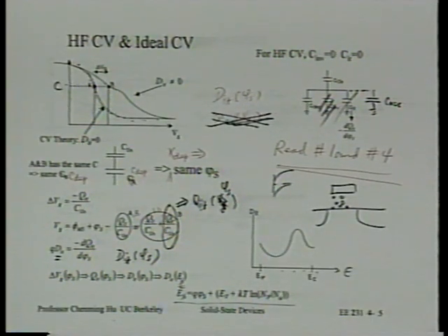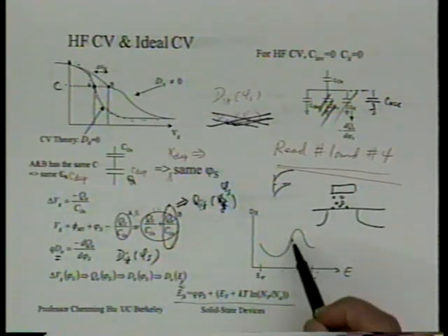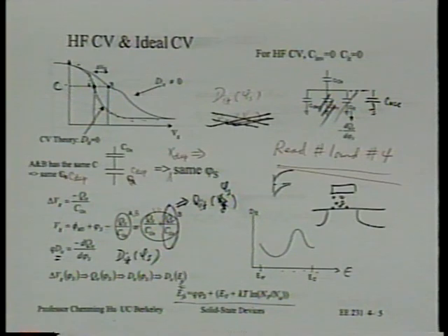When you see this peak, in my mind, I consider it really a discrete energy level, but because of our measurement inaccuracy it gets broadened out. But it's also possible that it's truly broadened just by the environment of this trap, this being an amorphous material environment. So in that sense, it's also continuous.